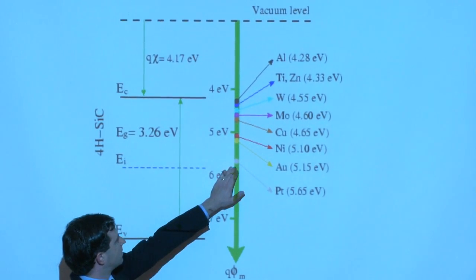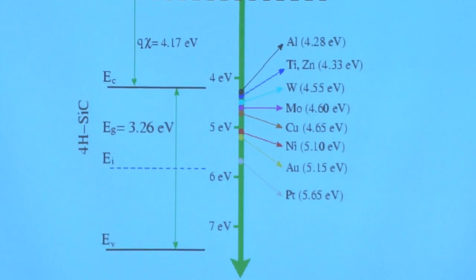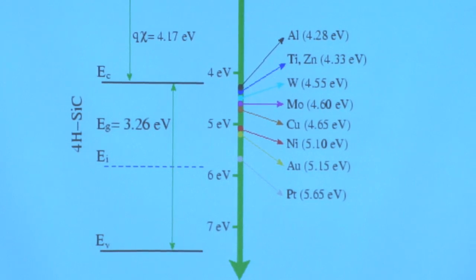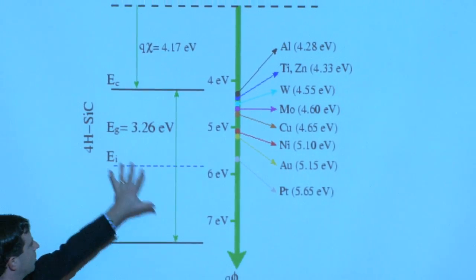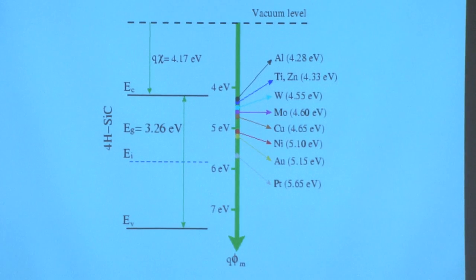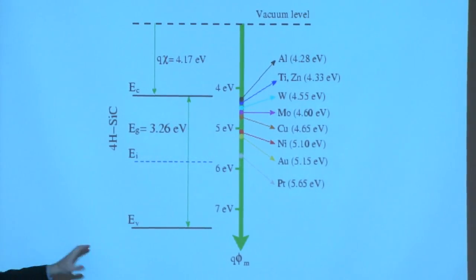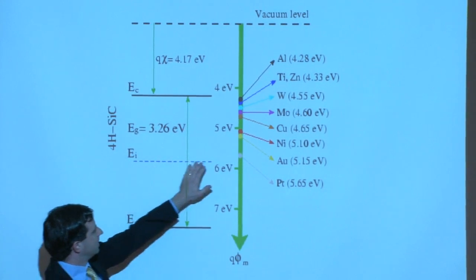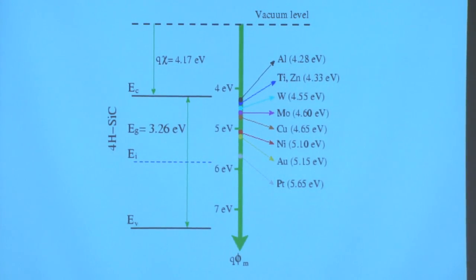But this gives you a sense of where the Fermi energy of the metal would lie relative to the vacuum level, and how that would match up against your arbitrary semiconductor. This one here happens to be a silicon carbide material, but if you happen to be working on a different semiconductor and place it right here, you can see where your Fermi energy would lie relative to the work function of the metal if you line up the vacuum levels. And this gives you an idea already of how the bands will bend once you adjust the position of the metal to match up the Fermi energy inside of your semiconducting material.